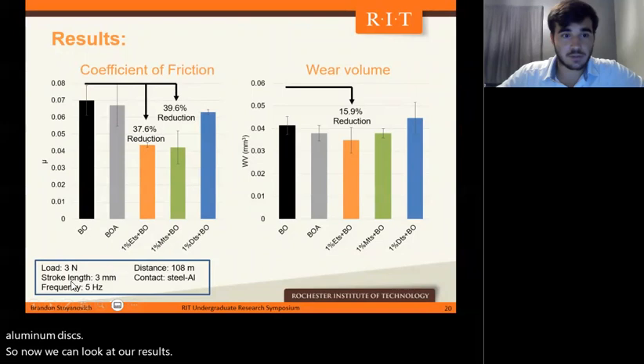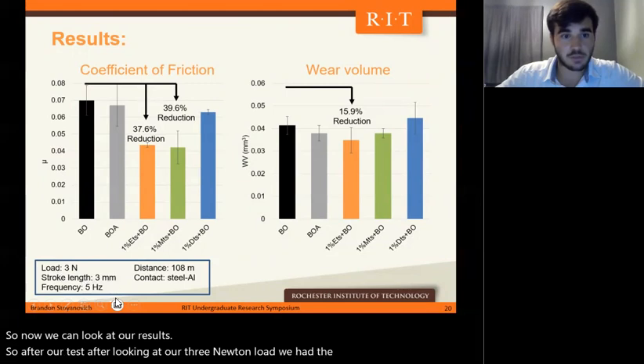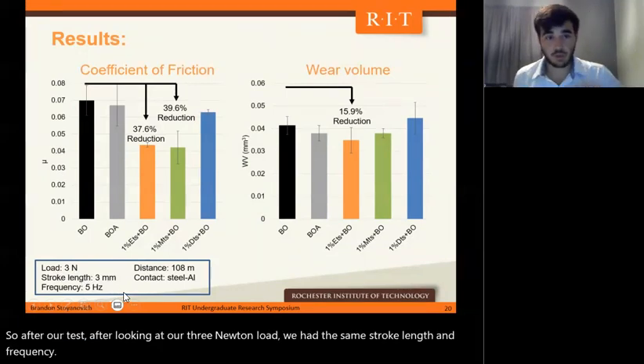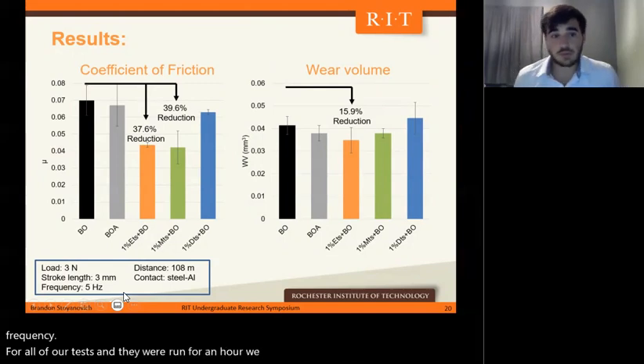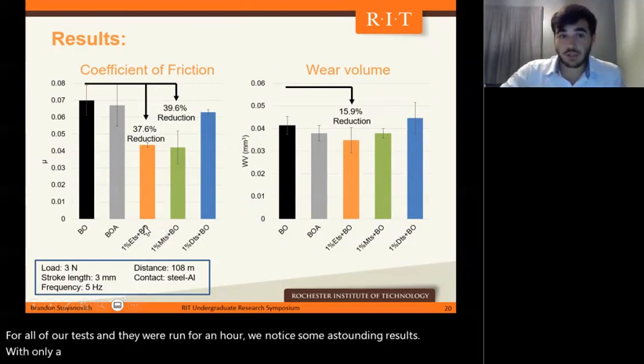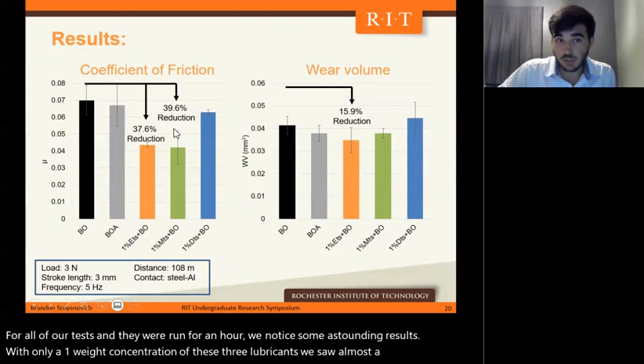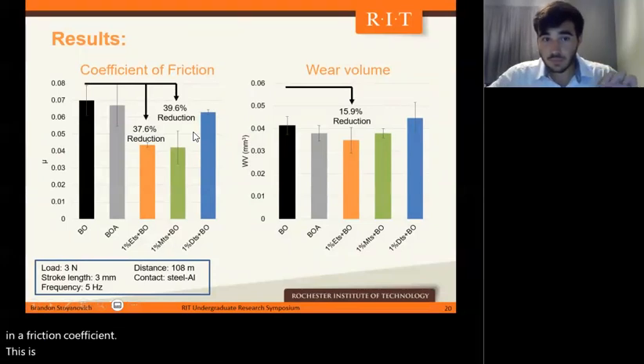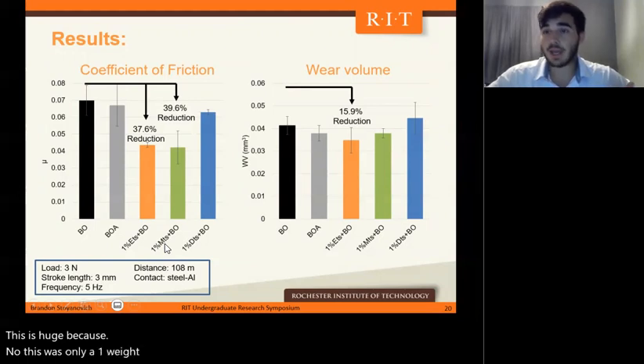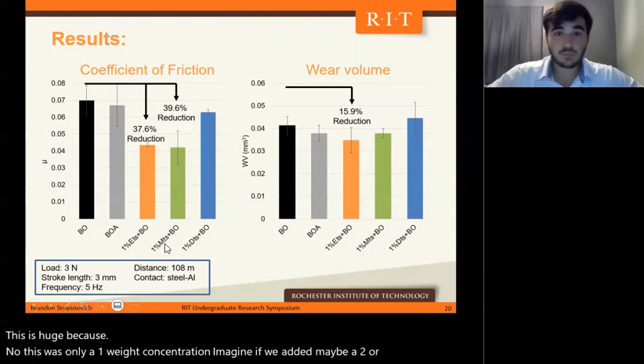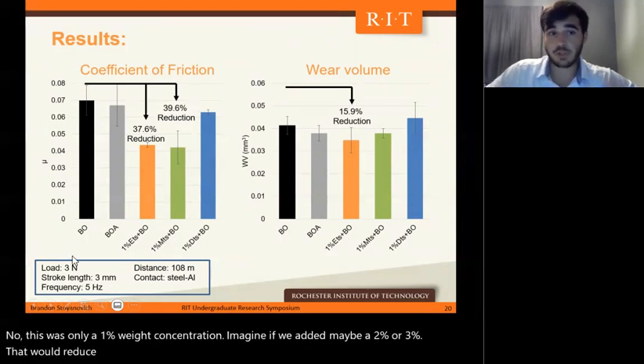After our test, looking at our 3 Newton load, we had the same stroke length and frequency for all of our tests, and they were run for an hour. We noticed some astounding results. With only a 1% weight concentration of these 3 lubricants, we saw almost a 40% reduction in the friction coefficient. This is huge because this was only a 1% weight concentration. Imagine if we added maybe 2% or 3%. That would reduce wear and friction across the board in many applications.